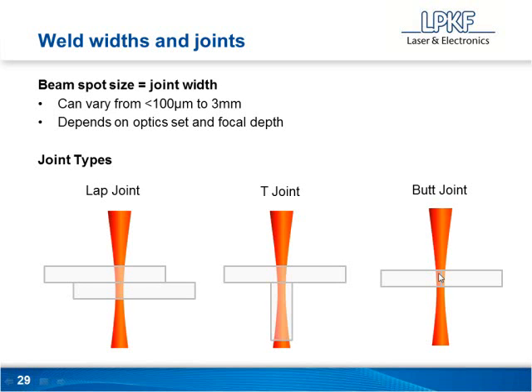That being said, Tony, I know we have experience because of the volumetric heating. The plastics tend to swell together more, and because of that, we can actually overcome more gaps. What's your thought on that? Yes and no. I mean, it is a laser welding process, so as with any other laser process, the tolerances have to be much tighter because you're using a much smaller heat source. And so yes, the better the tolerance, the easier it is to weld.